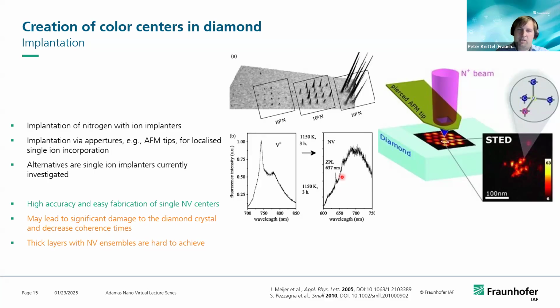The drawback is that you actually generate significant damage that can, again, decrease your coherence time, but especially decrease the stability, meaning the NV center that we use is in the negative charge state. If it discharges to a neutral state, we cannot make use of it anymore. And if we have charge traps in the diamond generated by this treatment, the NV will discharge to this NV0 state. So that's a bit of a disadvantage of this method. The other thing is that a thick layer with high concentrations of NV ensembles is very hard to achieve in this way. Also to have it homogeneously over a certain area.